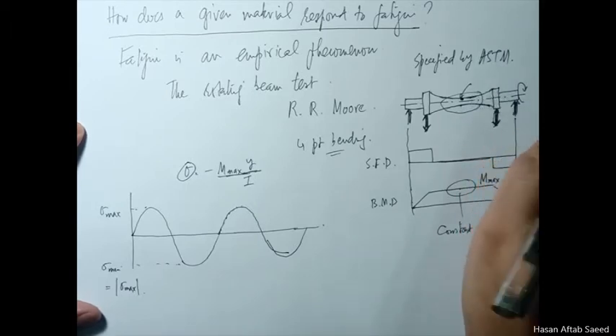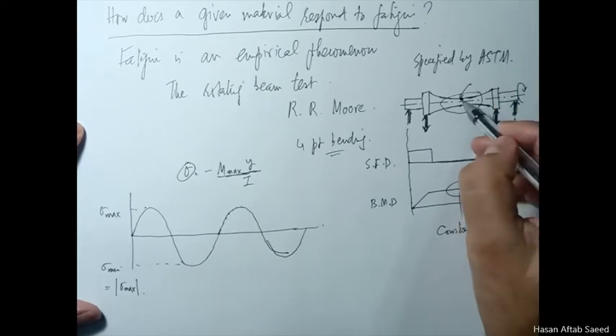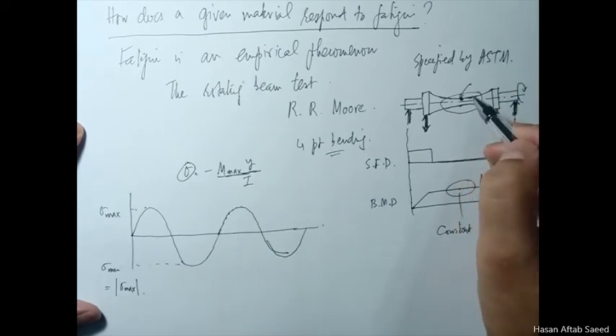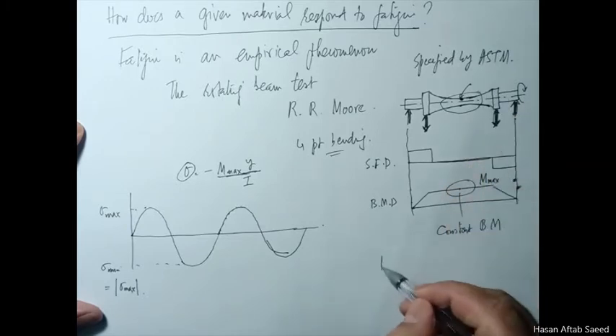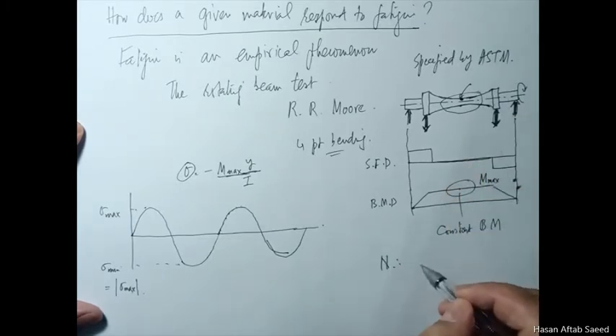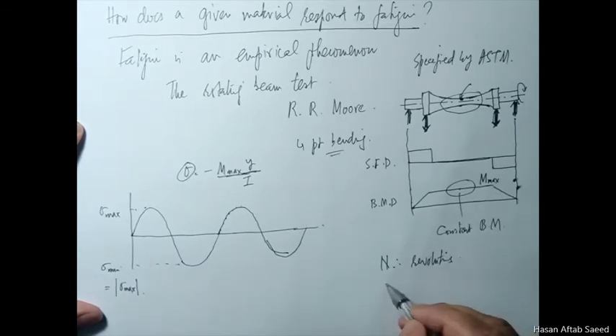Some cracks will initiate and then they will grow, and they'll keep on growing until a time when critical crack length is achieved, and then it will just break in two. At that point, the number of cycles, revolutions, are recorded for that stress level.